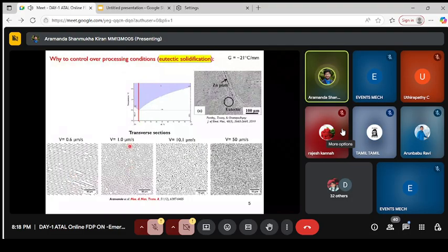And when we go further and further increasing the velocity, we can see very fine zinc, all of the same fraction. The only difference is that the big one is split into very small pieces inside the material. So when we do any mechanical test or any different type of test, this material behavior and this material behavior is different. So with the same alloy, we can create different internal structure, and that can be made into a good advanced material.